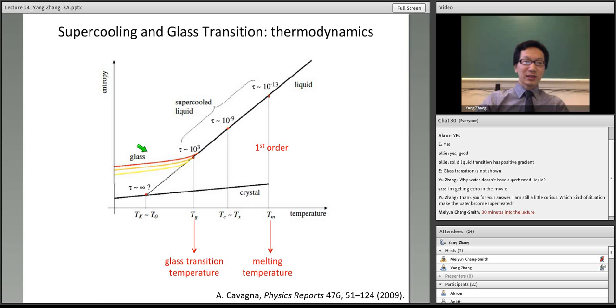Fortunately, when you change the cooling rate, the glass transition doesn't really change much. The glass transition always lies in a very small range, although, again, it's not very well defined. It depends on how you cool the system, how you prepare the thermal history of the system. But roughly speaking, you can define the glass transition around this temperature. And the typical cooling rate is about 10 K per minute or sometimes 20 K per minute. They won't change your glass transition temperature a lot.